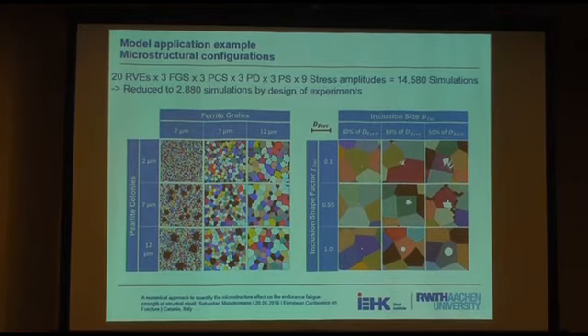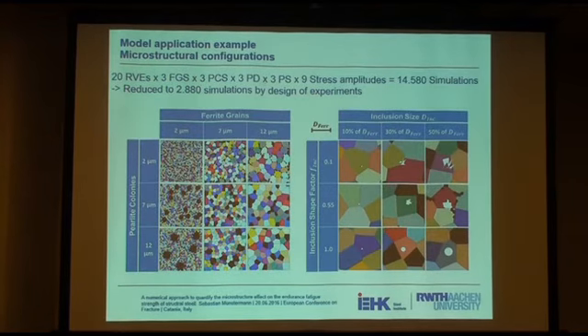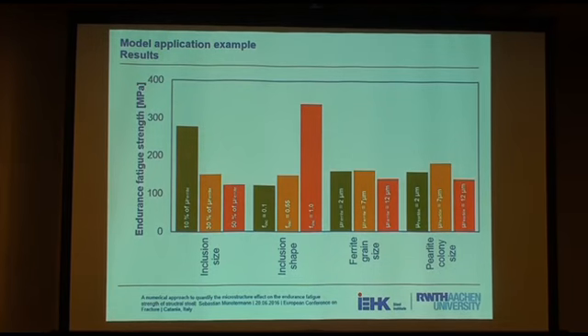We have tested, that's difficult, we have tested almost 14,580 configurations for our microstructure models, because we varied 3 ferrite grain sizes, 3 pearlite colony sizes, together with also 9 configurations of the inclusions, the particles. We made, as I mentioned, 20 RVEs per configuration on 9 stress levels. In fact, we then used design of experiments to reduce the number of simulations to be performed. And here's what turns out.